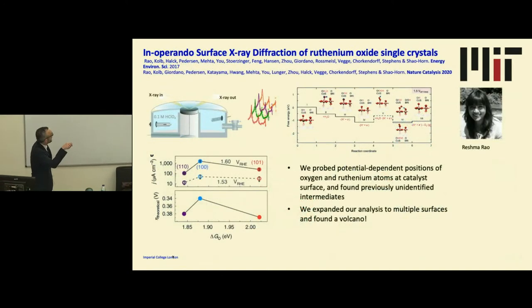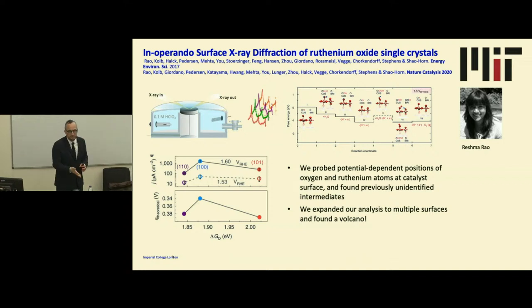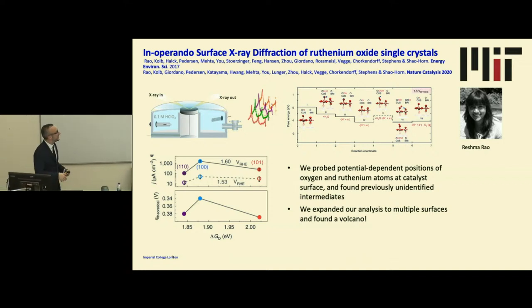What was really nice, at Imperial College and MIT, is that I started working with Reshma Rao. Actually, I taught Reshma, who's now a lecturer in the department, and we started collaborating. We used surface X-ray diffraction. We could probe on a single crystal, similar to the platinum crystal shown before, the position of the different ruthenium and oxygen atoms. Under applied potential, we found previously unidentified intermediates. We even expanded our analysis to multiple surfaces, and we found a volcano. So it was quite nice as a proof that we can start to get atomic scale insight into catalysts controlling water electrolysis.